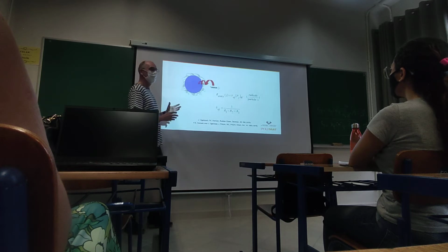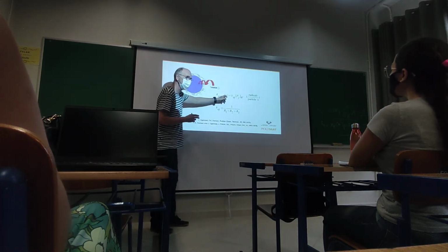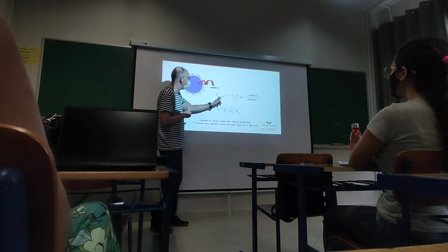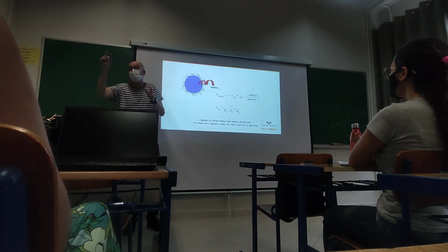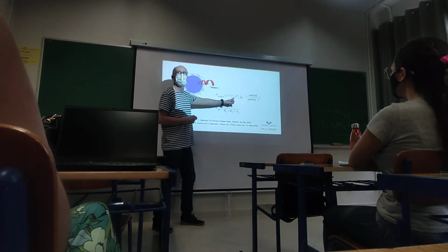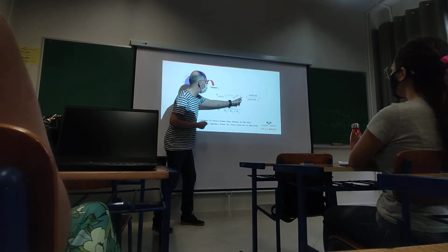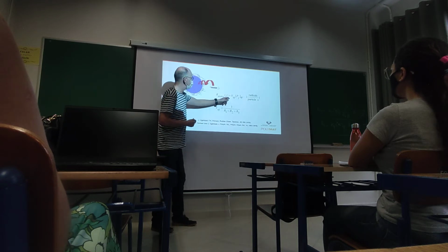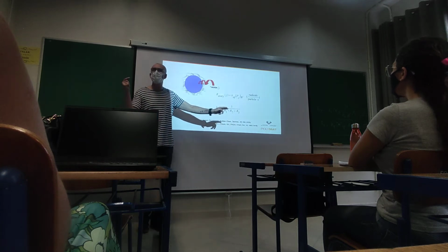So in general, what is done is to assume that the rate of entry, which depends on the length of the radical, so that's why it's length dependent. Here, the rate of entry depends on J, which is the length of the radical, so the number of monomer units of the radical, and it is equal to an absorption coefficient that depends on J, times the concentration of this size of radicals in the aqueous phase,